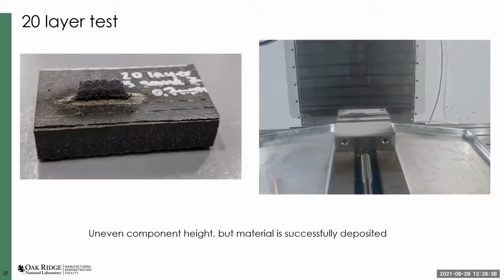So this was really promising because we now know that we can build up enough layers of metal that, even if the polymer were to start melting or to start degrading further, we would still be able to build up enough metal to support itself before the polymer is so negatively affected by the DED process that it's no longer useful as a support structure.